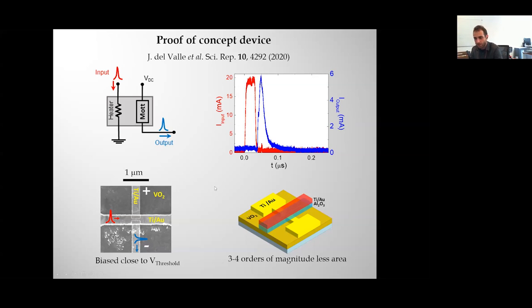The pity is that when we started this project, the idea was that we were going to get an output that was larger than the input. This was going to be biased close to the firing point so that any stimulus coming from here would be enough to create a much larger response, so that the input would be smaller than the output. And that is very important because if you want to use only this device as a neuron, you don't want to use amplifiers or anything else. If you need to amplify your signal, that's more circuitry, and you're losing the scalability. Unfortunately, we were not able to get an output that is larger than the input, but there is no reason why we shouldn't get it.